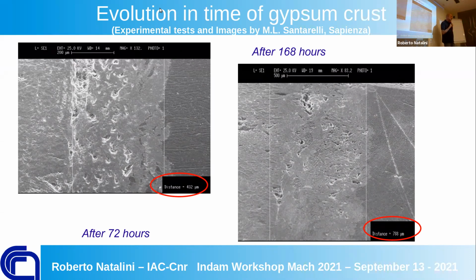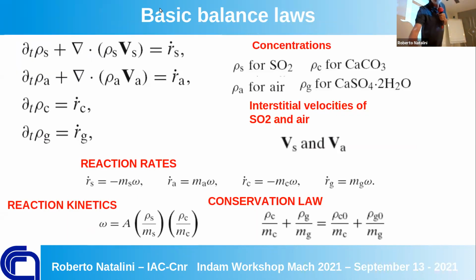There are some statistics like, okay, we have seen in a paper that some monuments in Milan were polished some years ago after 50 years of exposition, and they found 50 microns of crust, and they said, okay, 1 micron per year, but that's not the real speed, that's the measured speed. And so understanding what's the real speed of growth of this crust is crucial also for restoration practice. And now I have a lot of slides, so maybe I can go faster.